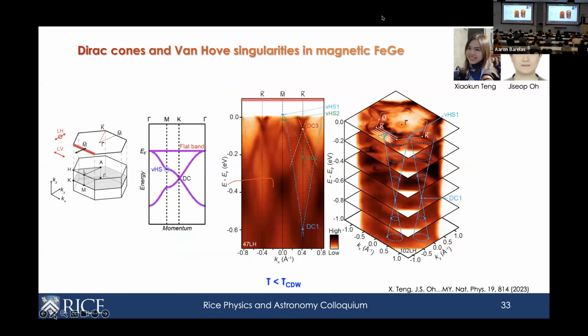So this is data collected by Xiaokun and also our postdoc Jisop. And so here, let me guide you through this. The way to read this is the energy versus momentum data, raw data. And this is the constructed three-dimensional view of this. So this is energy, and this is Kx and Ky. First of all, we can see the Dirac crossings here from the series of circles that shrink down and then expand out, right? And that matches the prediction of this Dirac crossing at the K point. Also, we can see that when this goes up, they actually meet at the end point in the Brillouin zone, forming this expected Van Hove singularity point, right? But how do we actually show this is the Van Hove singularity point?